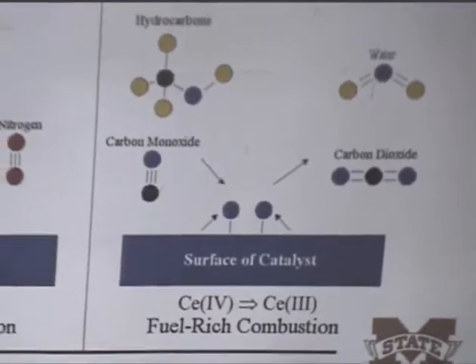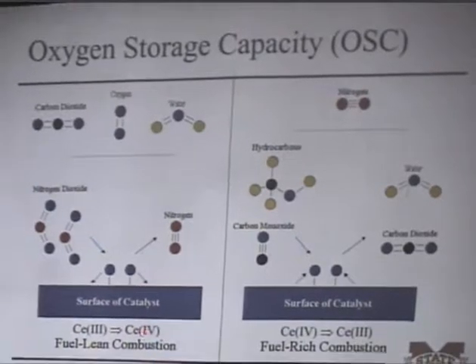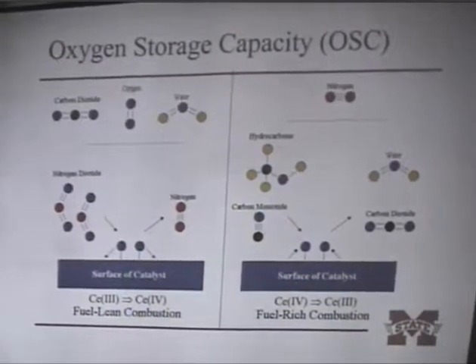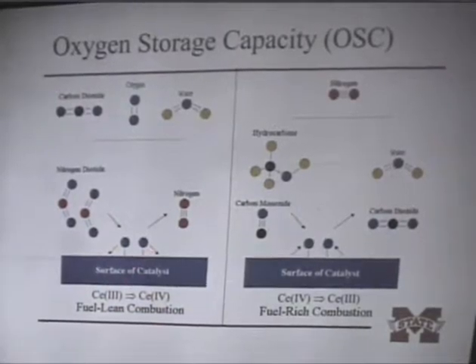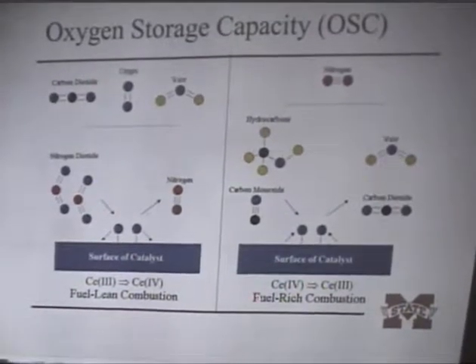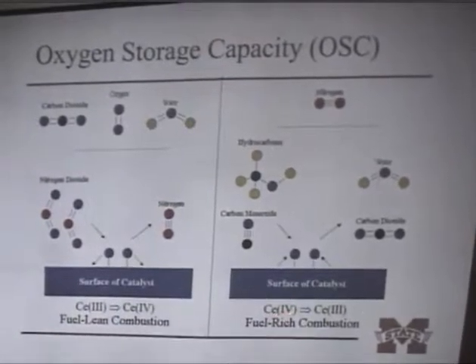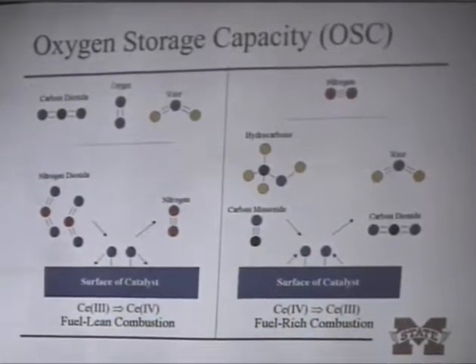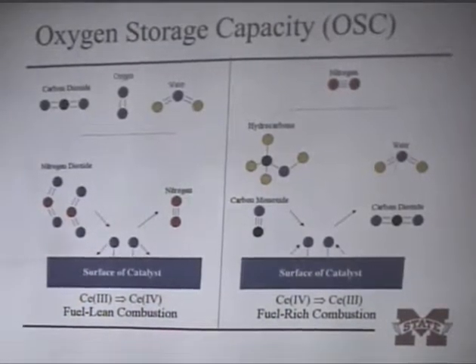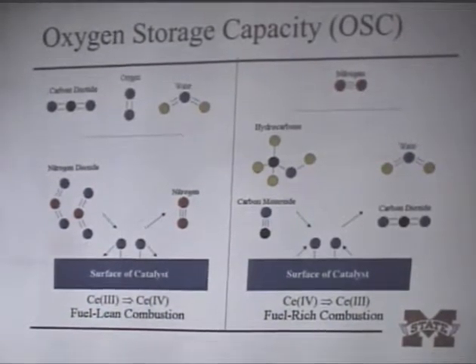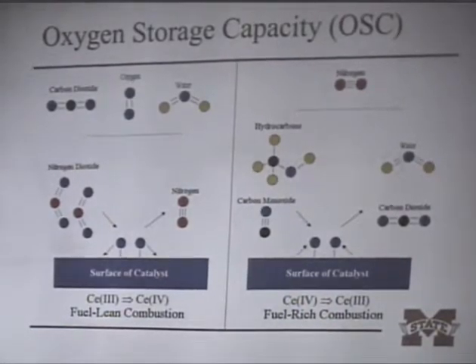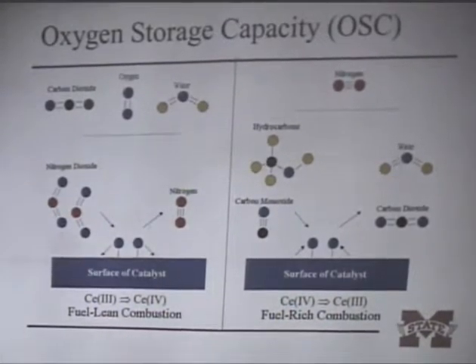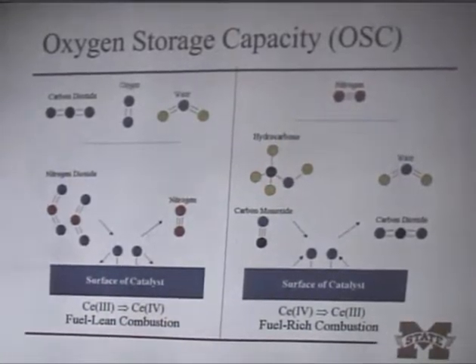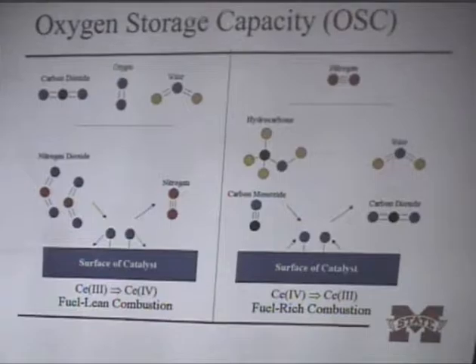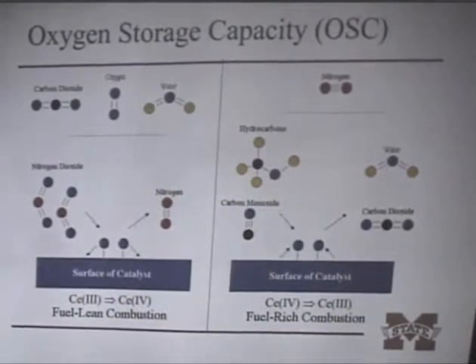Under fuel lean combustion conditions, or oxygen rich, we see a change in oxidation state from cerium +3 to cerium +4. In essence, we store oxygen in the lattice of the material under these conditions. When we have fuel rich or oxygen lean, we see a change in the cerium oxidation state from +4 to +3. We release oxygen, and this way we can have a source of oxygen regardless of the environment. So we have to have cerium oxide around to allow the +3 to +4, +4 to +3 change in oxidation state, so that we have a constant and plentiful supply of oxygen.